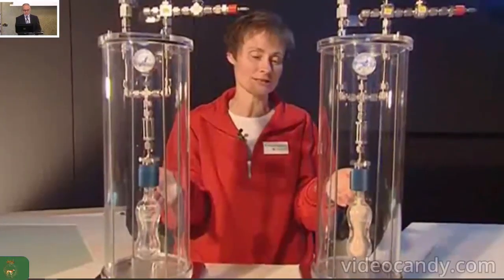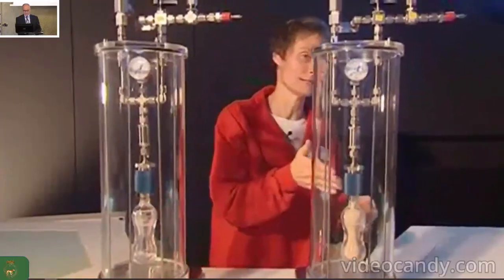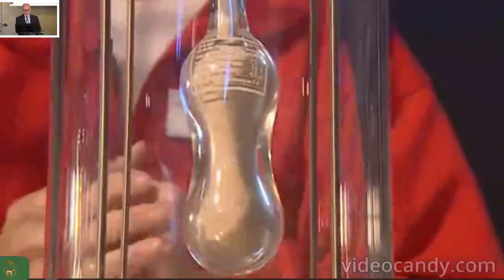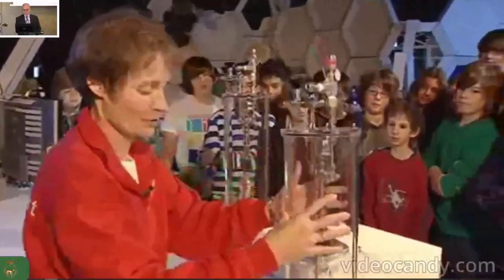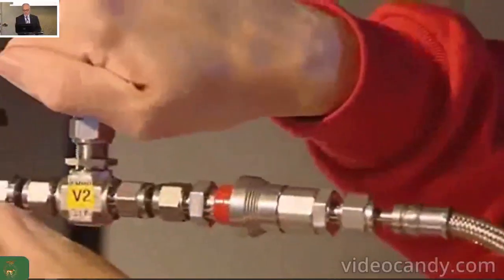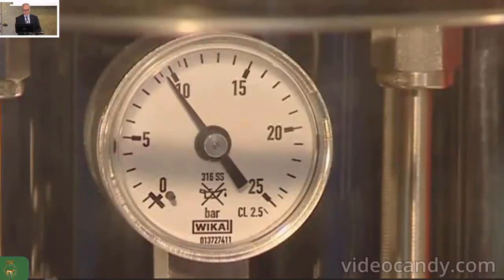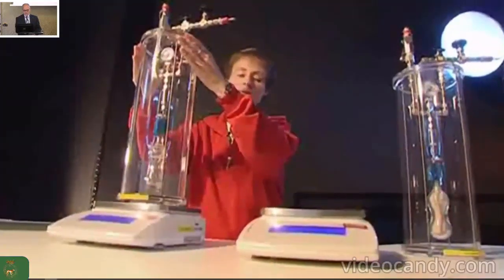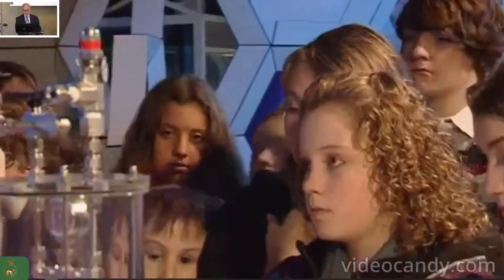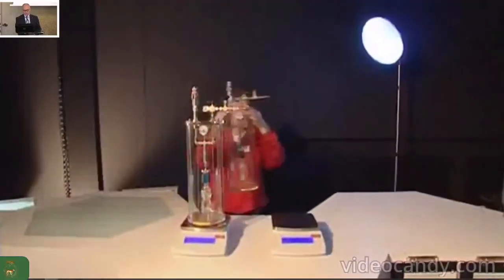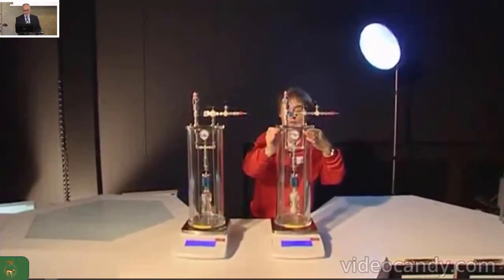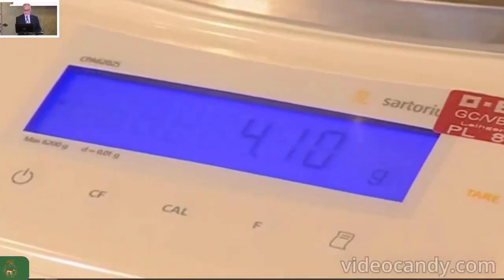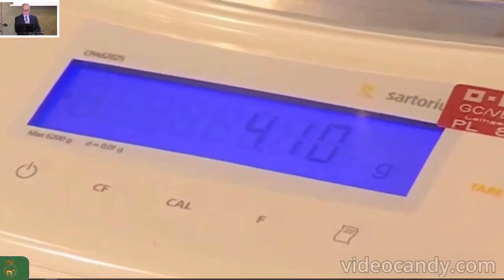The pear-shaped glass container on the left is empty. The glass container on the right is filled with a MOF material. A vacuum is created in the container without the MOF. This container is then filled with the gas at 10 bars of pressure. The apparatus with the empty glass container is now weighed using scales. Exactly the same procedure is repeated using the glass container with the MOF. The scales prove it. The MOF container has more than triple the amount of gas inside for the same amount of pressure.